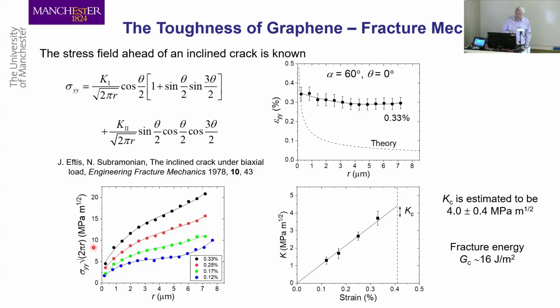We can work out the K factor. The K factor is a function of strain. And then we get to propagation at 0.41, which is the critical K, Kc. And we have 4 measurements here of the crack stress concentration increasing. And then suddenly the crack propagates, and we can work out the fracture toughness of 4 megapascals root meters, which is not a lot. So this is a massively strong material, which is not that tough. A fracture energy of 16 joules per square meter or so.